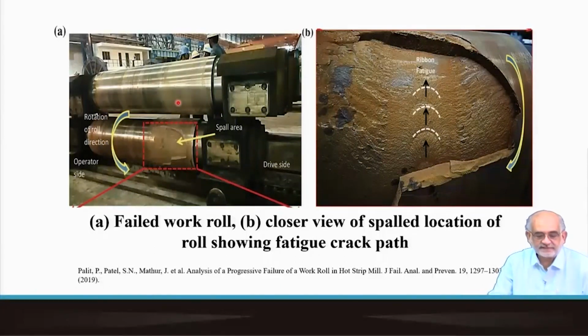Now, before we begin, take a look at this very large roll, and each one of them would be weighing several tons and made out of alloy steels, very expensive. A single roll could cost about 1 crore or even more, and they have a certain service life. Now, let's say either due to manufacturing practice or fault or defects created during the manufacturing of the roll itself, or during the processing, that means rolling of various feedstocks, either the temperature was too low or the feed was actually given in a non-uniform manner so that the stress got concentrated over a period of time.